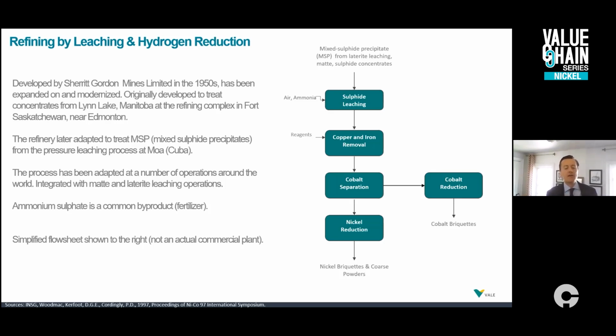You can take a variety of sulfide feeds. So originally this process was developed to treat concentrates from northern Manitoba. But it can also treat matte, and can also treat precipitated intermediates like MSP, if you've heard of that. So this material, the nickel and other metals, are leached in acidic ammoniacal solutions. There are then a series of impurity removal steps that are again customized to the feedstock, customized to the size and other processes in the refinery.